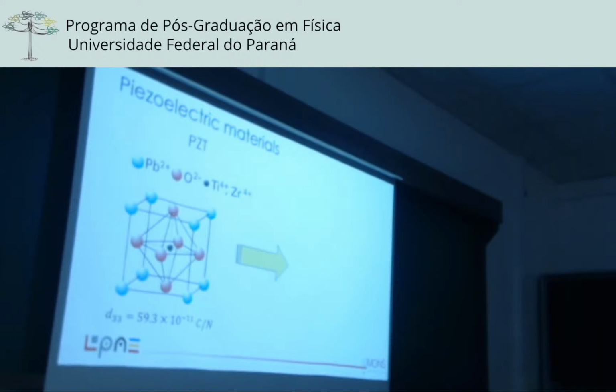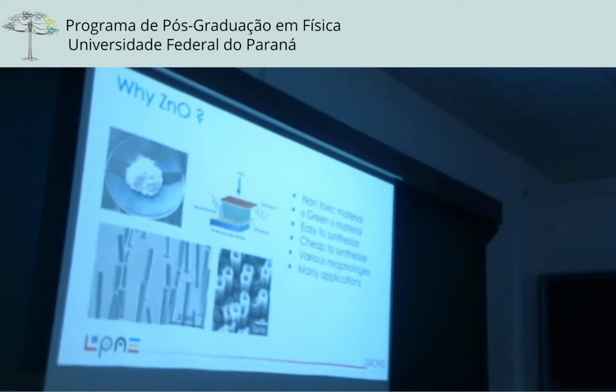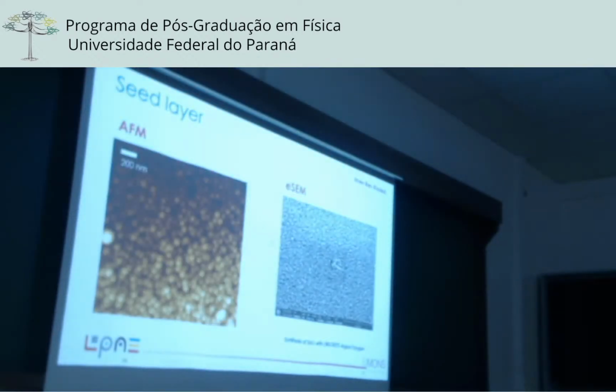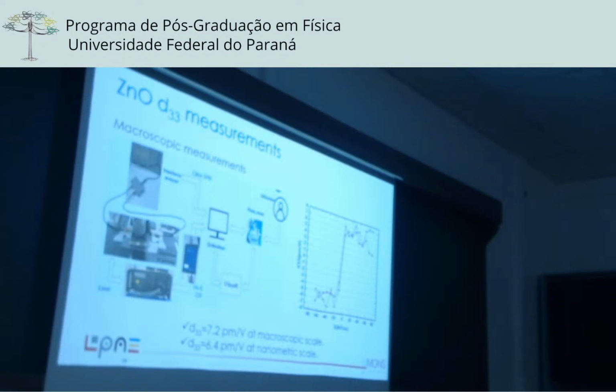So the idea is to replace the lead, and the idea was to use, for instance, zinc oxide nanowires or nanoparticles. Why? Because it's not toxic. It's a green material, cheap to synthesize, and you can tune its morphology, and we can use it for many applications. And this is the work of Imen, that Camilla knows, and this is the eSEM, and this is the AFM. And this is what Imen was measuring macroscopically. So we have something like 7 picometer per volt, and with AFM, by using the technique I described before, we are about 6, so we are not far, at the local scale, from what you are measuring at the macroscopic scale. And you can push on this nanowire like this, and measure the piezoelectric properties.